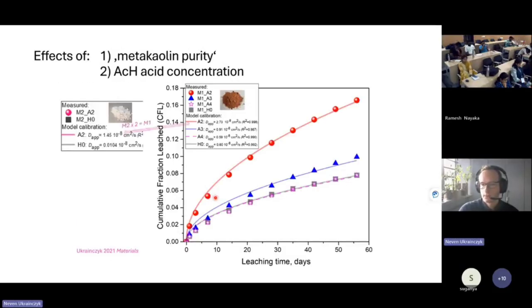And here are some results. You can see the cumulative fraction of leached potassium with time, and you could fit it to the simple diffusion equation. The stronger the acid, the stronger the leaching of potassium. So this is the amount of leached potassium in the solution with time. And here you have it for water, for very low concentration of acid, for higher concentration of acetic acid, and for very high concentration of acetic acid. And this one was on the red clay geopolymer.